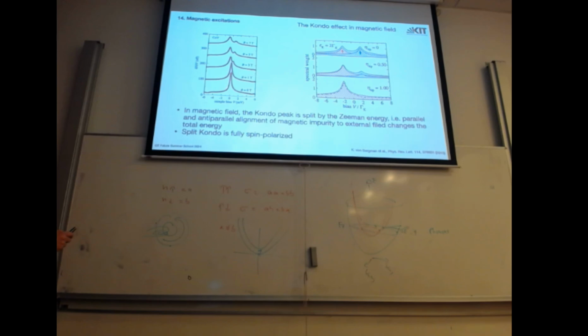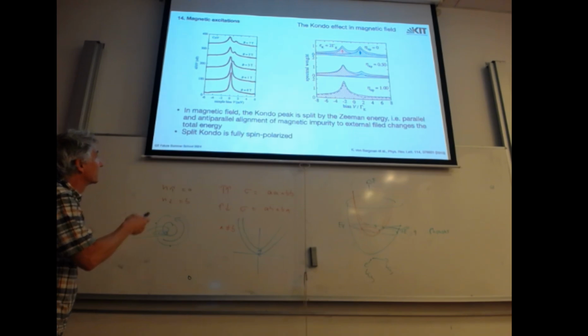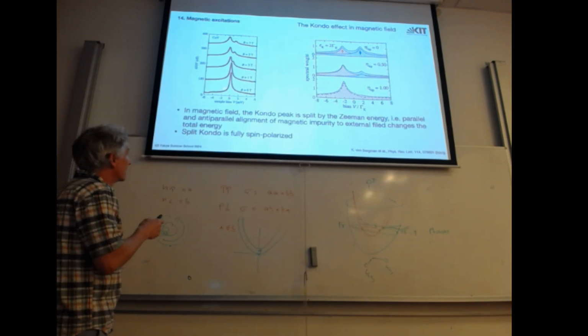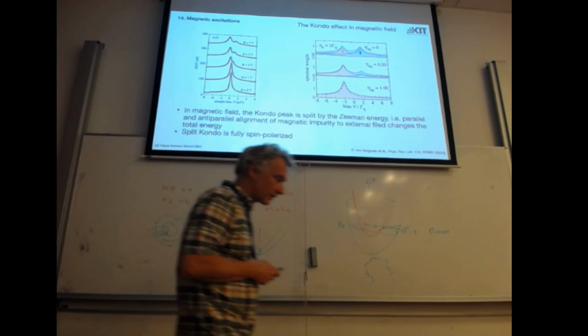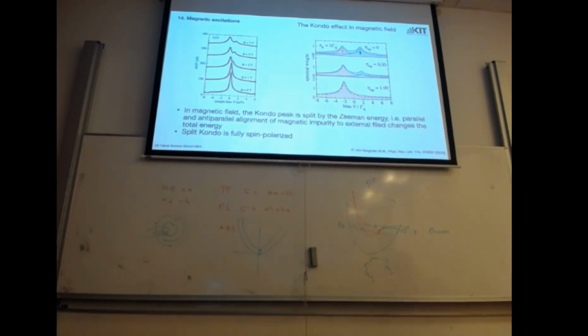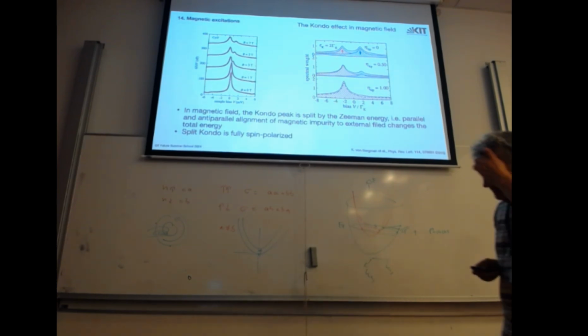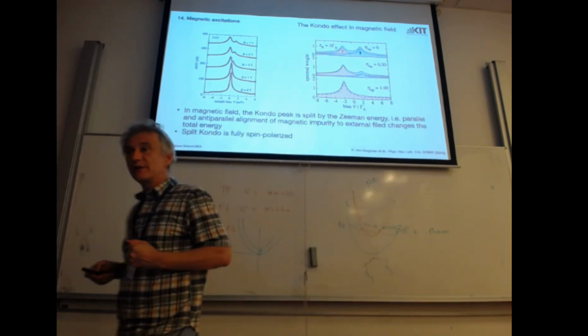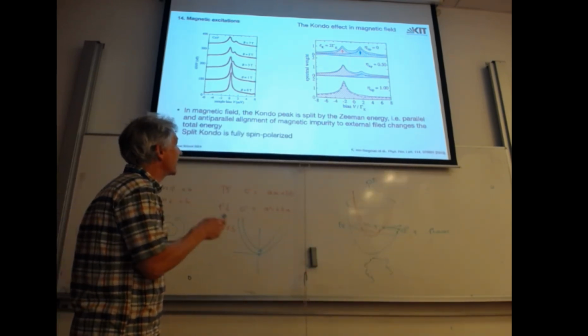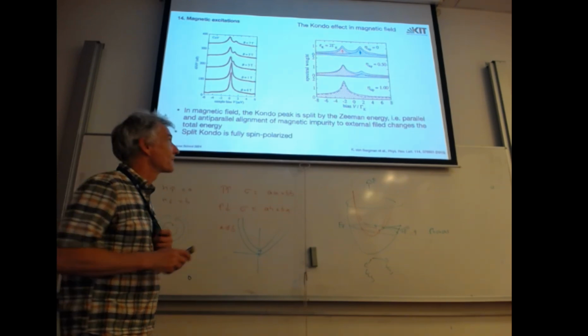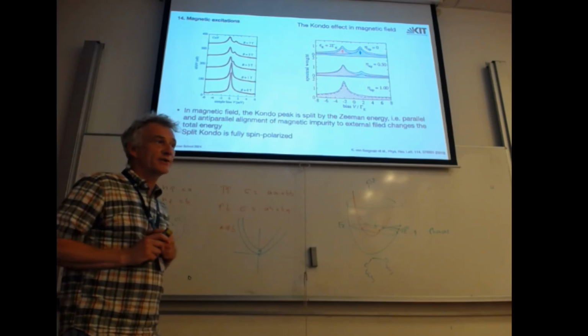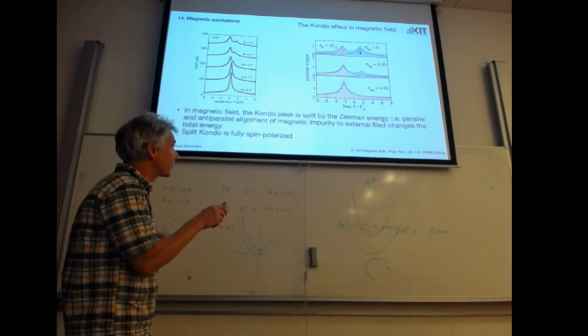You can also apply a magnetic field, and this will actually split this singlet and give two peaks. And the splitting is the g factor of 2 typically. And what I want to mention is that now the occupied part of this electron state will align with the magnetic field, and these pairs are actually 100% spin polarized. If you split the smaller peak, you can make a 100% spin polarized object with localized states.